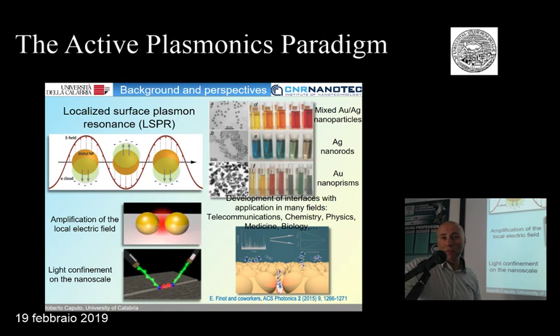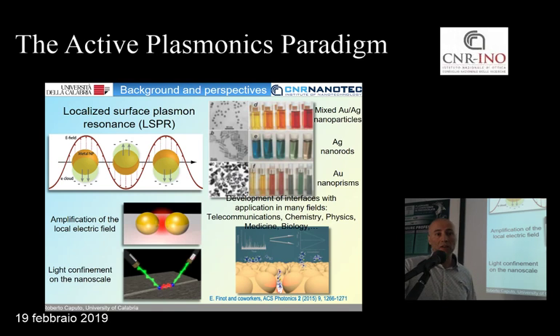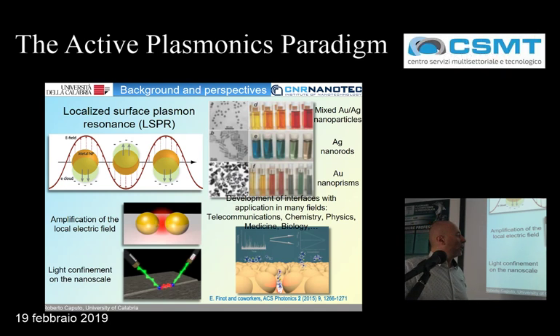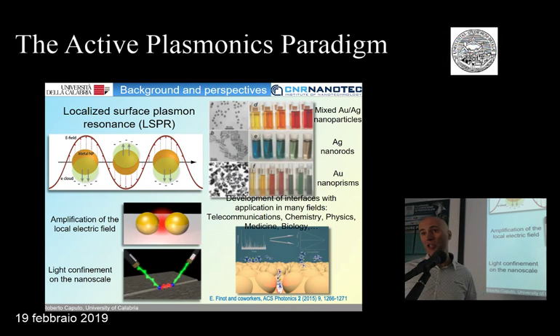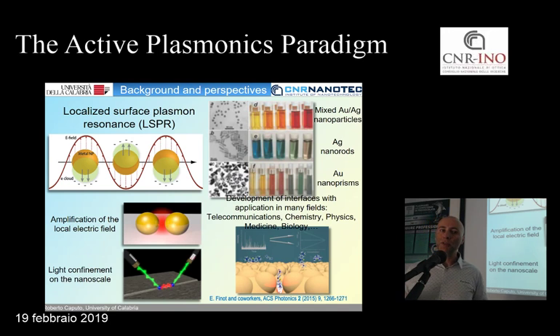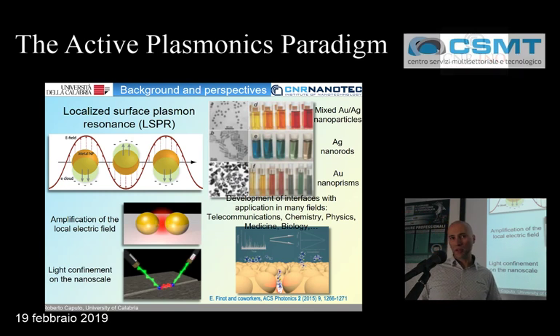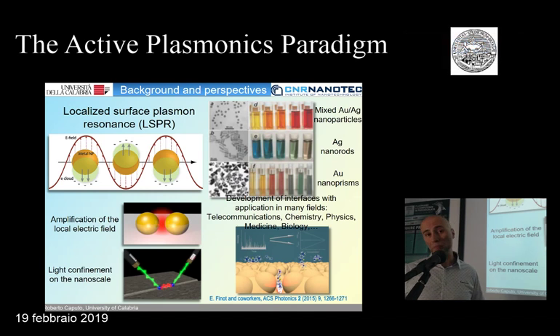And why do we want to study plasmonics? Because there are many possibilities in photonics, medicine, biology, chemistry. And in particular, it's very interesting because the nanoparticles, when they are very close to each other, show a particular behavior, which is called plasmonic coupling. So there is an overlap of the electronic cloud of the particles, which generates a shift of the plasmonic resonance of the single particle. So we will see this in more detail during this seminar, because this is the core of one of the mechanisms we use for inducing active plasmonics.